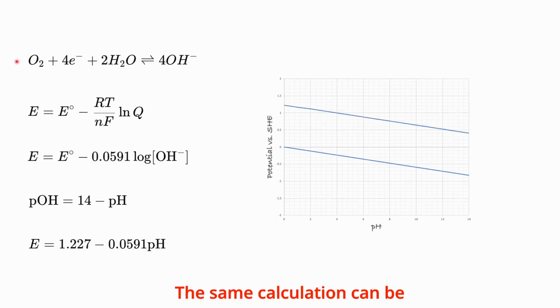The same calculation can be repeated for this reaction involving oxygen molecules and hydroxide ions. Upon working out the maths, we find that the equilibrium potential is 1.227 minus 0.0591 times the pH value. This equation can similarly be plotted on a potential versus pH graph, generating a second line. Above this line, oxidation is promoted, so oxygen is stable. Below this line, the reduction reaction is favored, so hydroxide ions are stable.